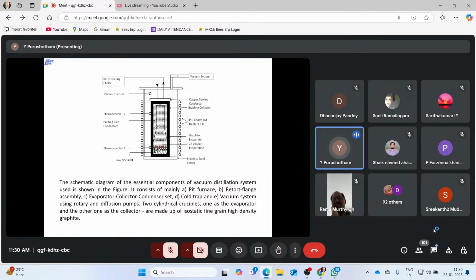In that particular batch, for example, if you are taking 1 kg of metal, whatever impurities are there, when we bring it up to the melting point of that metal, the low melting materials or impurities will simply evaporate. Since it is under vacuum, they will go to the top graphite crucible, and this top graphite crucible is attached with a cold water circulation.